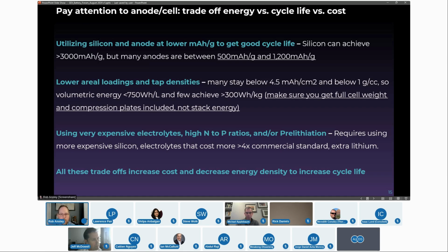Now, where things change is pre-lithiation. I do believe that you're going to see a huge improvement in energy and cycle life together with pre-lithiation and with some of these expensive electrolytes like localized high concentration that Sila was doing with PNNL. Why? Because the localized high concentration forms a more stable SEI, so you have a lot less lithium losses each cycle and less lithium losses during formation, but they're very, very expensive, like I was saying with SES. And then pre-lithiation, what does that do?